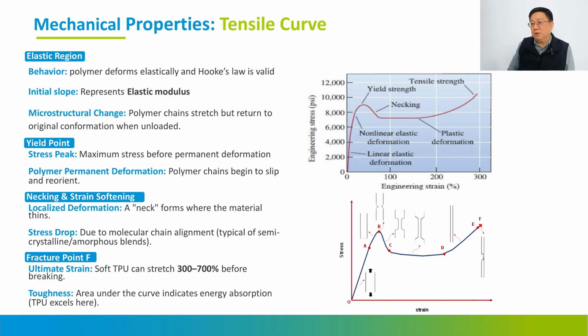However, the real world is not like this, because the aligner is loaded for a long time. Because of high temperature and the force difference in different areas, normally it will decay to a certain degree. Most of our performance products can still maintain about 75 to 80% force during the wearing period, normally 7 to 10 days. Right now, most people understand that if you use a good performance aligner, in 7 days you can already move the teeth to a predictable position. It has changed over the last 5 years. 5 years ago, people said we need to wear the aligner for 14 days. But right now, 7 to 10 days is enough to move the teeth. There is a lot of clinical data showing that it performs very well within 7 to 10 days.